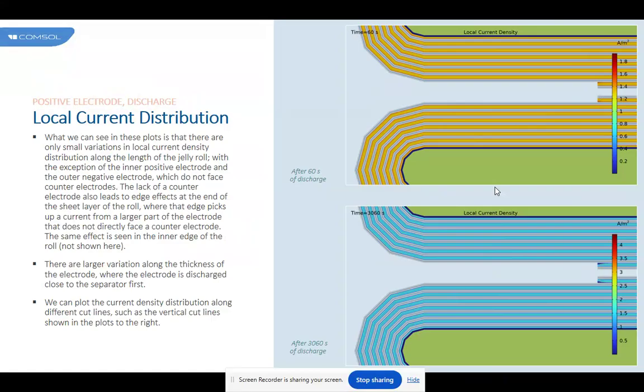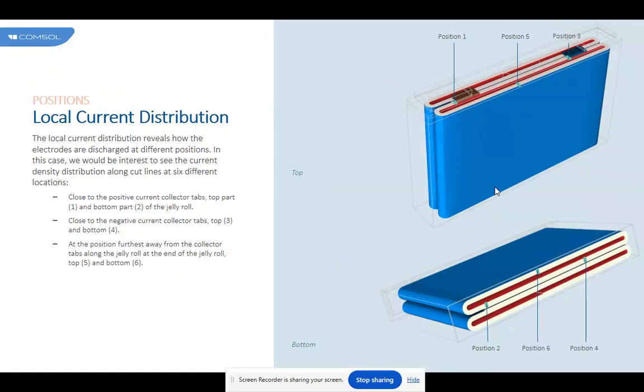Local current distribution. What we can see in these plots is that there are only small variations in local current density distribution along the length of the jelly roll, with the exception of the inner positive electrode and the outer negative electrode, which don't face counter electrodes. The lack of a counter electrode also leads to edge effects at the end of the sheet layer of the roll, where the edge picks up current from a larger part of the electrode that doesn't directly face a counter electrode. The same effect is seen at the inner edge of the roll, not shown here. There are larger variations along the thickness of the electrode, where the electrode is discharged close to the separator first. We can plot the current density distribution along different cut lines, such as the vertical cut lines shown in the plot to the right.